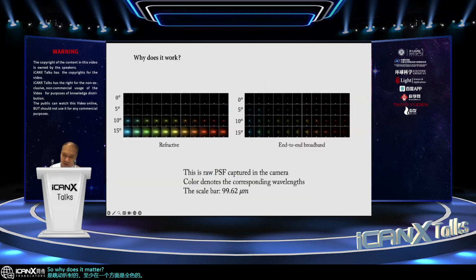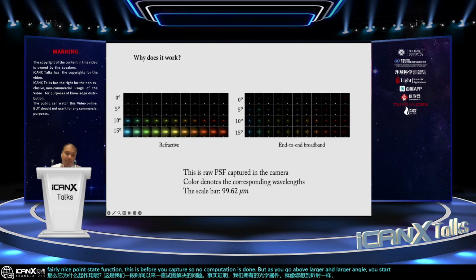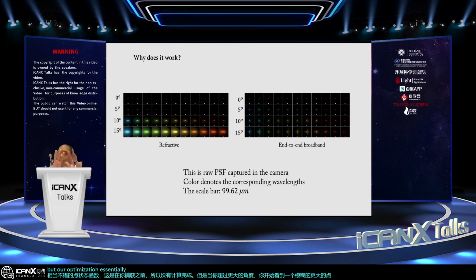This is something that we have been trying to answer for quite some time. It turns out that if you think about refractive, you have a fairly nice point spread function. This is before you capture, so no computation is done. But as you go to larger and larger angles, you start seeing a blurrier, bigger spot, as we expect from spherical aberration, right? But our optimization is essentially trying to uniformly make the PSF as small as possible over all the wavelengths and all the angles. And this is exactly what we have. These points are slightly bigger than these points. But overall, we get a much narrower size than what we can get with refractive. So this really is the design insight we came up with.